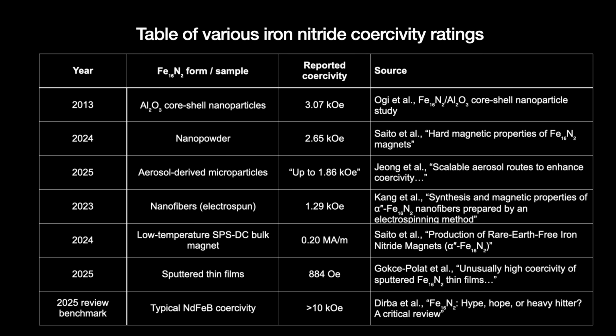Neodymium iron boron magnets have a coercivity of 10 kilo-Ørsted, or higher. Ørsted being how strong an opposing magnetic field needs to be to reverse the magnet. Iron nitride, by comparison, ranges from 1.29 to 3 kilo-Ørsted, depending on the magnet's physical form. Small particles coated with other materials tend to do better.